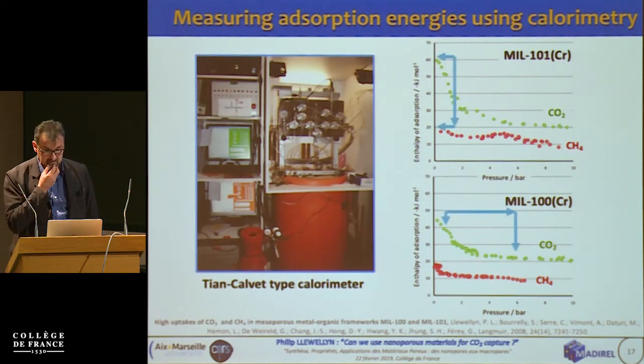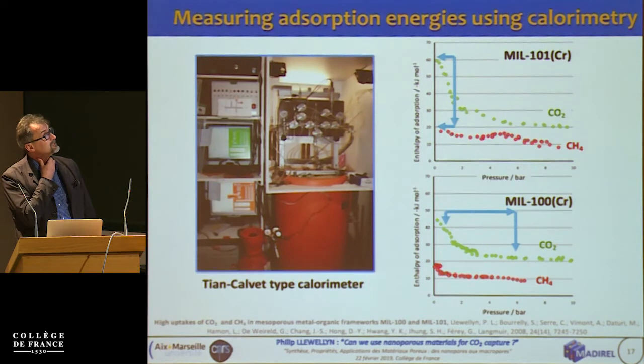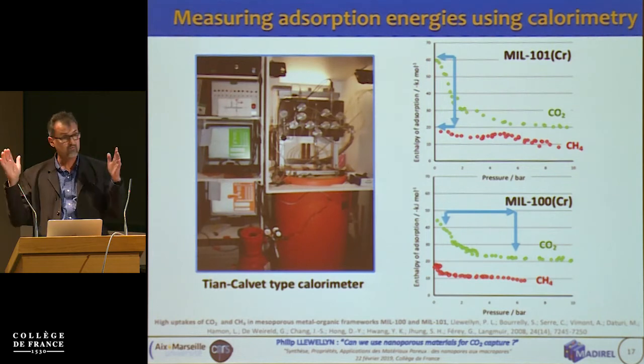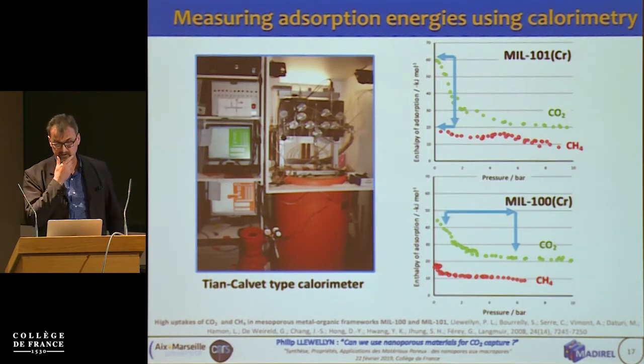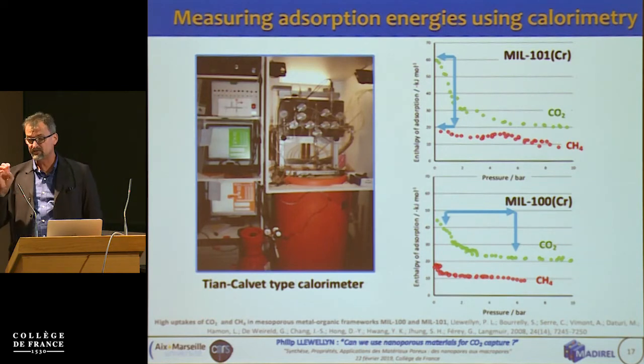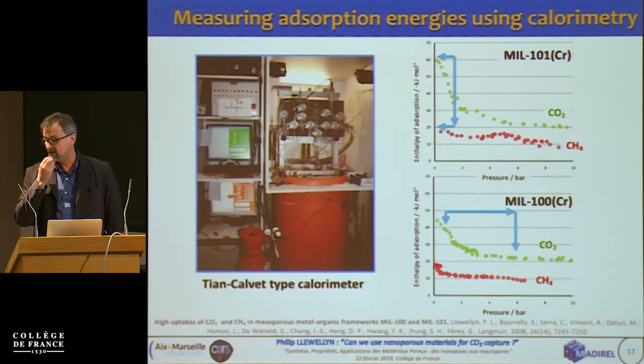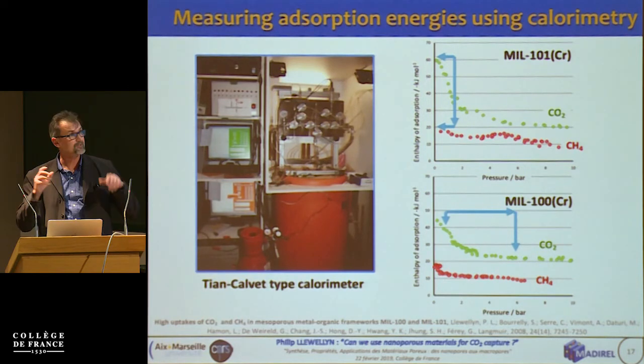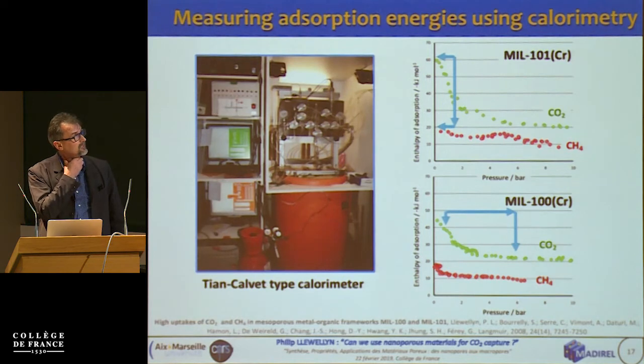We can get from this either the difference in initial uptakes, so the difference at the top here between the CO2 and the methane, or at the bottom, we can just integrate over a pressure range the heat that is given out. The heat is an important parameter. It's a huge parameter in terms of process. Any small amount of heat in a process has to be managed at some point, so it's something that we have to take into account.